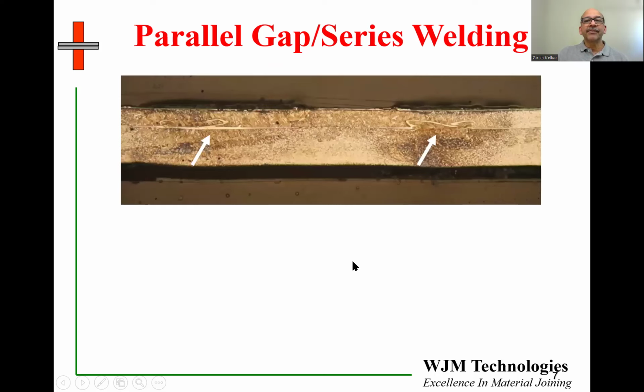Here's an example of a cross-section of a parallel gap weld where you can see the top tab, which is thinner, and the bottom tab, which is thicker. That helps to push the current down. In the cross sections, you can see the nickel plating between the 2 has been disturbed over here, and the nickel plating has also been disturbed over here.